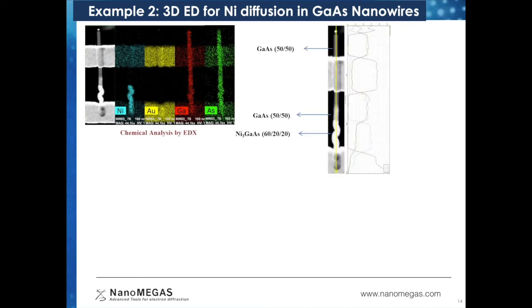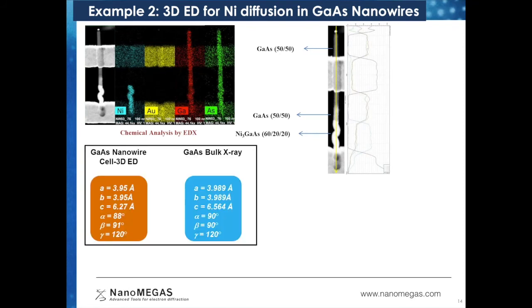The second example is not from my work. The second example is studying the nickel diffusion of a gallium arsenide nanowire by thermal annealing in a nitrogen-rich atmosphere. First, EDX was performed, and from the chemical analysis, 2 different phases across the nanowire were observed. And then the authors moved to 2 different locations where there are 2 different compositions.